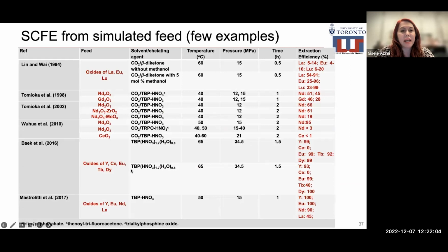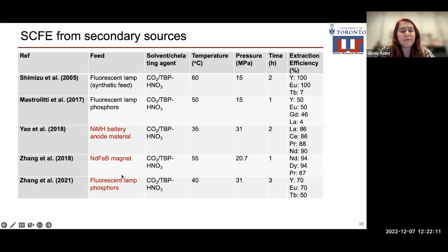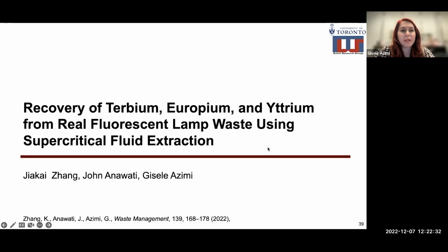Several studies in the past have looked at the recovery of rare earth elements from mixed oxides or pure oxides. Only a few have looked at the recovery from real products. For example, Shimizu and Mastrolitti looked at fluorescent lamps, but the extractions they achieved were low. And my group has looked at nickel metal hydride battery, neodymium iron boron magnet, and fluorescent lamps with promising extraction efficiencies.